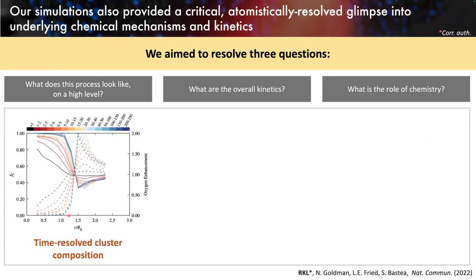As I go outward to, we'll call this 1.25, that's roughly where the interface between the nanoparticle and the reactive soup that solvates it exists. Beyond that, we're moving out into the fluid. The solid lines here are telling us about the carbon composition, the dashed lines are telling us about the oxygen composition.